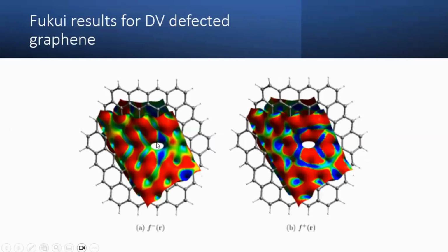Now this is nothing but the double vacancy defect. Here you can see octagons and pentagons. After the defect formation, the electron transfer process is not homogeneous. In ideal graphene, an electron can be removed from any portion, but after the double vacancy defect, an electron can be removed with most probability at certain portions and less probability at others, because again the planarity will break and the carbon-carbon bond length will change.